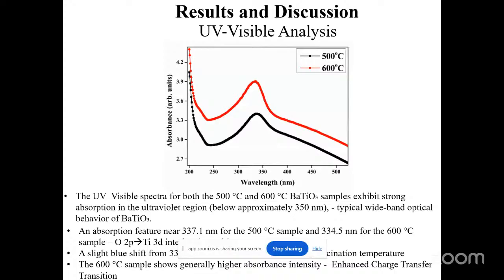Results and discussion. The UV visible spectra of both samples show strong absorption in the ultraviolet region below 350 nanometers, which is typical for wide band gap material like barium titanate. We observe absorption peaks at 337 nanometers for the 500 degree Celsius sample and 334 nanometers for the 600 degree sample. This absorption corresponds to the oxygen 2p to titanium 3d electronic transition. A slight blue shift is observed with the increasing calcination temperature, indicating changes in the electronic structure and improved crystallinity.